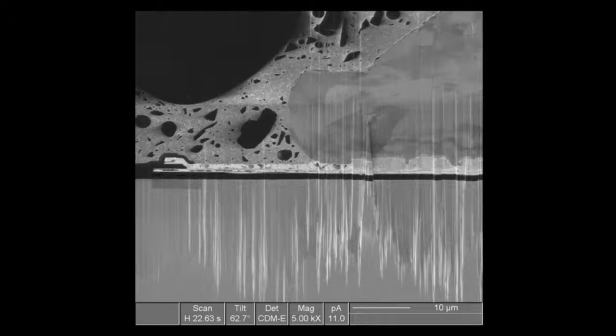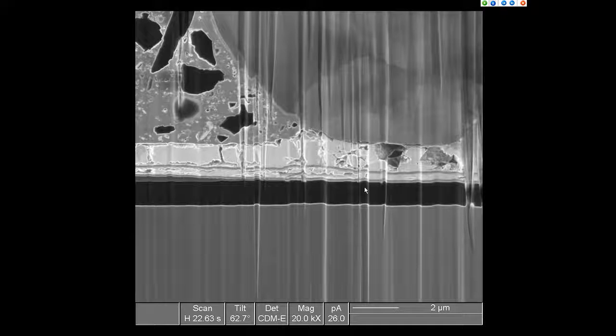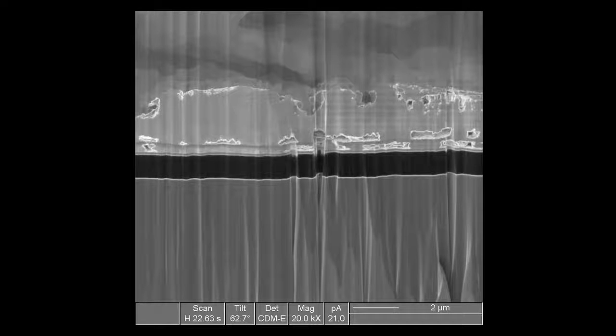This is an example of a wire bond, and it's the type of wire bond that would actually be inside one of these packages on an electronics component. And so here we have a gold wire bond coming down onto an aluminum metallization pad. The aluminum pad has good intermetallic growth, which means it was bonded well initially, but you can look at the aluminum metallization and see that it's all chewed up because of some sort of corrosive attack. And so, of course, if this corrosive attack continues, then that wire bond will come loose and the device will no longer function properly. And so identifying the nature of the contaminant that caused this etching is critical to making sure that other devices in the lot won't fail in the future.